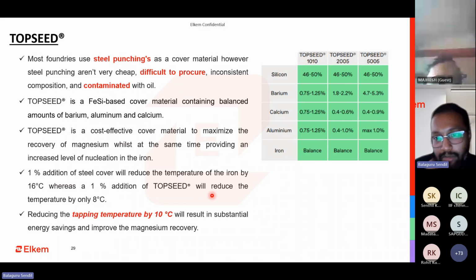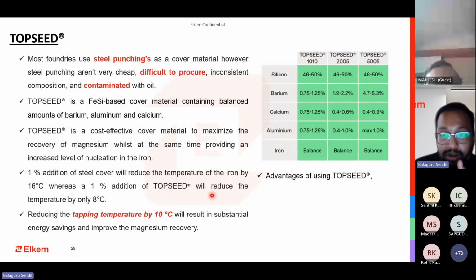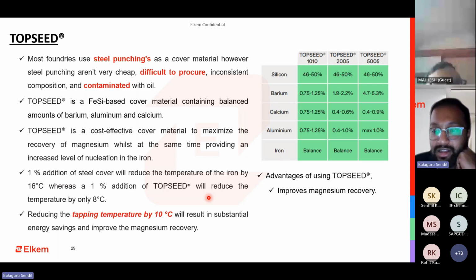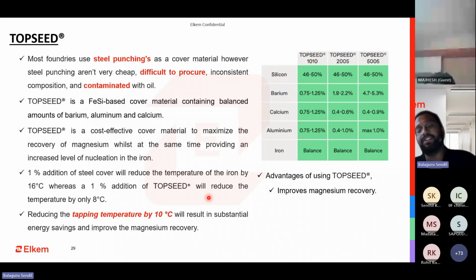So Top Seed in combination with a low magnesium addition percentage will give you the cost benefit. Also, you will have a power benefit. You will not compromise on your end pouring temperature. That will remain the same because the Top Seed takes less heat to melt and the reaction will be very late. You will not need to superheat the metal so much. The advantage is that it also improves your magnesium recovery. With Top Seed, we have proven in multiple places the recovery is more than 80%. So people who are using 1.4, 1.3, we have brought it down to somewhere between 0.8 to 0.9. That is the addition percentage you can have.